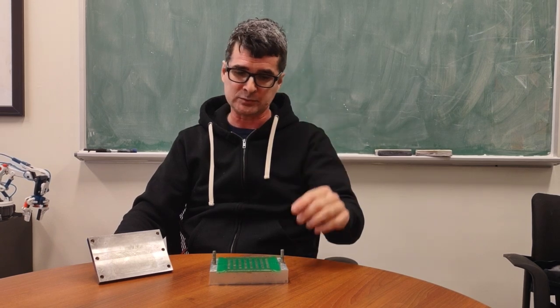And we then wanted to learn what it is about these materials that makes them better. And when we tried to plot correlations, you'll see it in the paper, it's very hard to learn anything. Even parameters that we know are important, like the crystallite size, show very poor correlations. When we plot transition metal dissolution versus the crystallite size, we get a box. And we see a lot of boxes in the correlations in this paper.